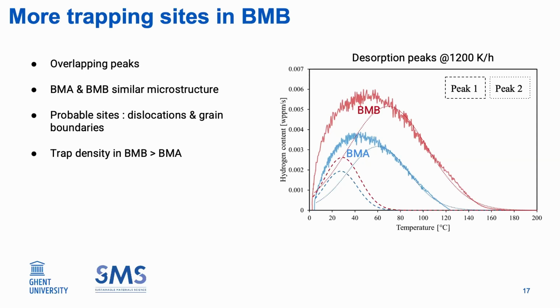If you remember, BMB has a lower ferrite grain size, which indicates that the grain boundary density in BMB is higher than that of BMA. So this can also lead to its high hydrogen uptake. Indeed, more work is needed here to know the activation energies of the traps for hydrogen desorption, to know actually which kind of traps are involved in such behavior.